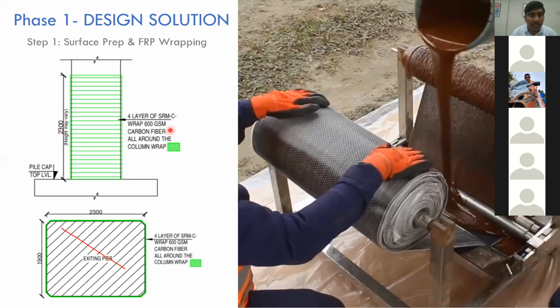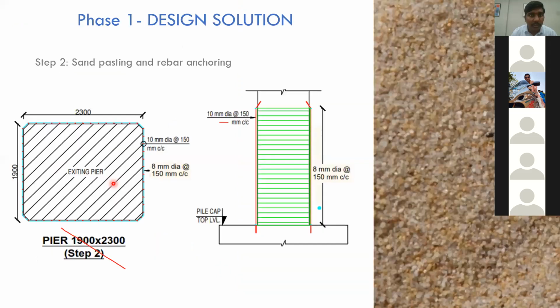Okay, so this is the stage 2. After doing this FRP wrapping, like 4 layers of carbon fiber all around the column, what you need to do is protect the FRP. Because it's a river, there are a lot of floating objects coming from the river, and they will directly impact the FRP and damage the fibers. Then it is of no use. So for that,